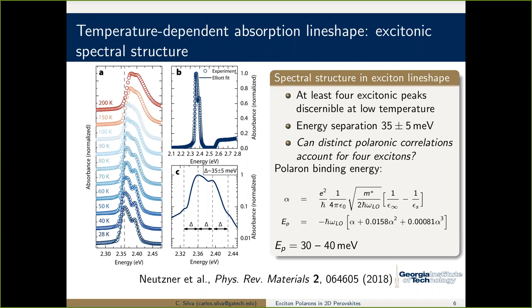Let me just keep driving this point that what we're seeing is that we have at least four peaks with separation in energy of 35 millielectron volts. I'm not going to get into the details of how we've ruled out the main contribution to this from those other models or hypotheses, but we then developed the hypothesis that these are distinct exciton polarons, just by noticing that the polaron binding energy in three-dimensional perovskites, as has been measured by a number of groups, mainly by time-resolved vibrational spectroscopy, is on the order of 30 to 40 millielectron volts.